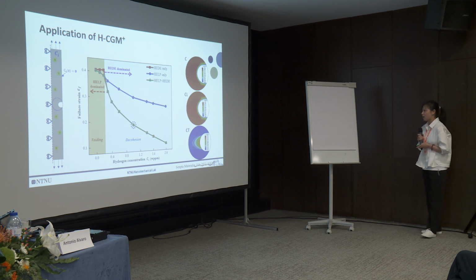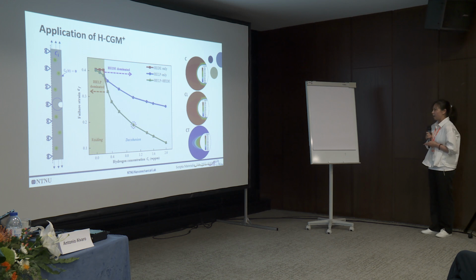These three figures show the total hydrogen concentration, lattice hydrogen concentration, and trapped hydrogen concentration. Here the lattice hydrogen concentration dominates, and the trapped hydrogen accumulates at the notch area, since this is the place where plastic strain accumulates.